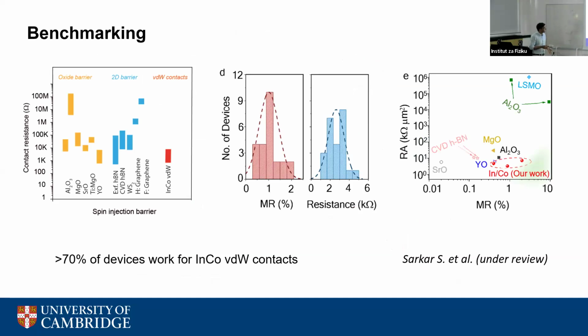And what I wanted to show is that, as I said, it's really challenging to grow these dielectrics. So all papers in the spin injection community report their devices on 1 or 2 devices, because I'm not saying it's not reproducible, but it's difficult to make high yield devices. For the first time, we show statistics, which has become very common for electronics, but is not so common for spintronics. We are showing that you can actually reproduce these for more than 70% of your devices, because it's a very scalable technique to just electron evaporate van der Waals contacts, and without the need for growing tunnel barriers, you can reliably introduce spins.